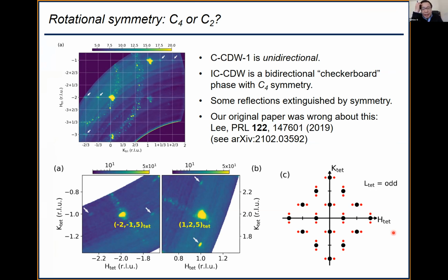Yeah, beautiful talk. So I was wondering, Peter, actually maybe one comment and one question. The comment is that in the process of understanding some still evolving experiments in these heavily hole-doped iron arsenides, we thought about how to link any density wave fluctuations at some particular Qs with the type of nematicity. And the statement is that so long as the density wave fluctuations are away from the iron-iron bond direction, you have a chance of getting nematicity that's 45 degrees rotated away from the direction that's picked in the usual iron arsenide cases.